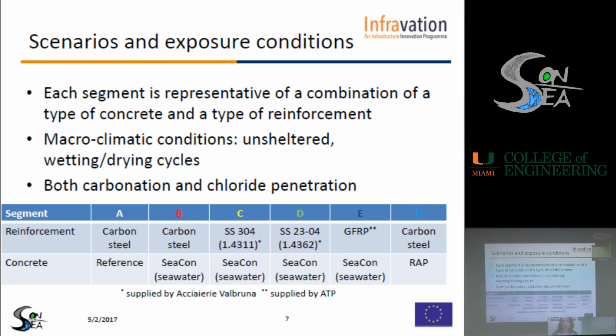As I said, each segment is representative of a different scenario, so a combination of type of concrete and type of reinforcement, as it is summarized in this table. So segment A is a reference, so carbon steel reinforcement in chloride-free concrete. Then there are segments B, C, D, and E that are all made with seawater concrete that contains seawater, and contain respectively carbon steel reinforcement, stainless steel 304 that is an austenitic grade of stainless steel, 2304 that is duplex stainless steel, and finally GFRP reinforcement.